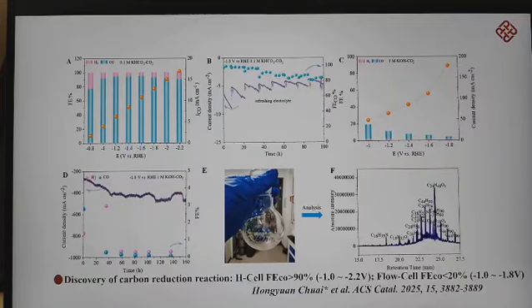However, under industrial conditions, the current density is usually greater than 100 mA per square centimeter. To evaluate the performance of our prepared carbon-based electrode under working conditions, we conducted flow cell tests. The results showed that within the potential range of -1 to -1.8 volts, the CO Faradaic efficiency was less than 20%, and almost no hydrogen was detected.